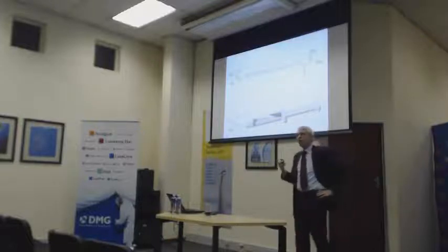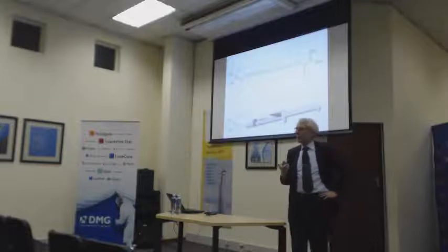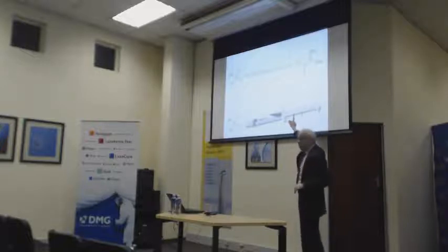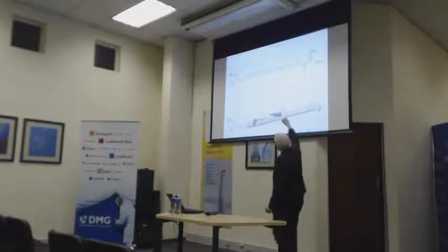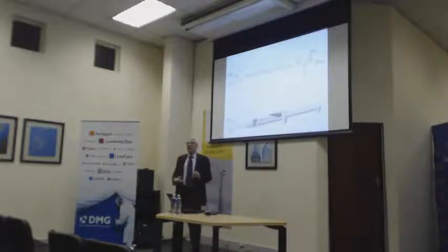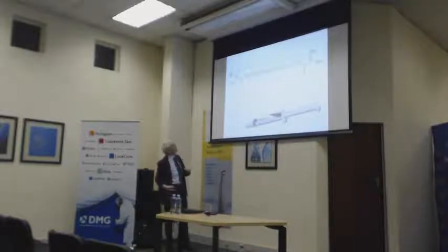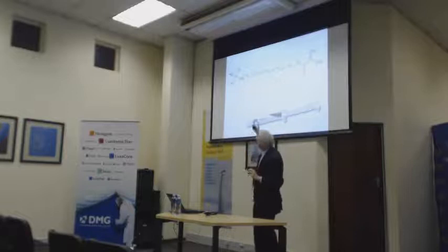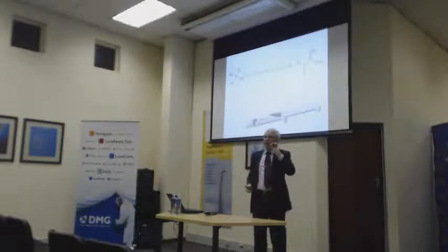And this is an interesting molecule. It's one very special molecule that is used in the formulation of some of these cements. Basically it consists of three parts. We have that very easy part here with a double bond, which lets it polymerize and incorporate into the resin matrix. Then we have a backbone, a linker, that connects it with the other part. And this is your usual phosphoric acid etching gel. If I just overlay this, then you see, aha, this phosphoric acid is basically becoming a modified phosphoric acid, and this part is actually able to bond to zirconia.